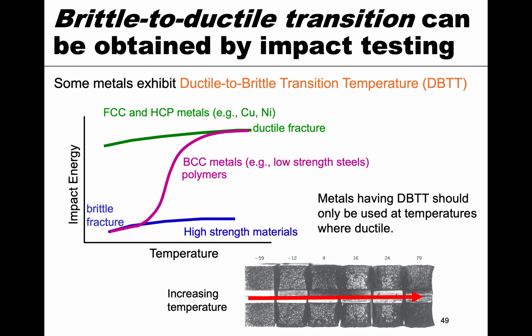So, obviously the Titanic, it wasn't planned for those kind of temperatures, and obviously that's an issue if you're going to be in freezing waters. So that's something to mention. And also, when you look at the surfaces of the fractured material, so this is a notched sample, and it's the two surfaces after. And you can see that if we go up to these really high temperatures, so this one is 79 degrees, you can see it's fairly rough, and there's a lot of deformation in the sample. You can kind of see this change in shape over here. It was normally a square.